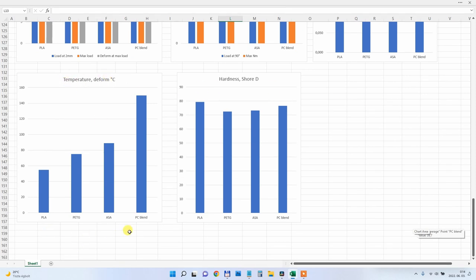Temperature, no surprises here, or maybe I should say this is a very pleasant surprise, PC blend. I thought it would start with deformation at approximately 100, maybe 110 degrees Celsius. But analyzing the footage, I noticed that only at approximately 150 degrees Celsius it starts with deformation. So this was a very pleasant surprise.